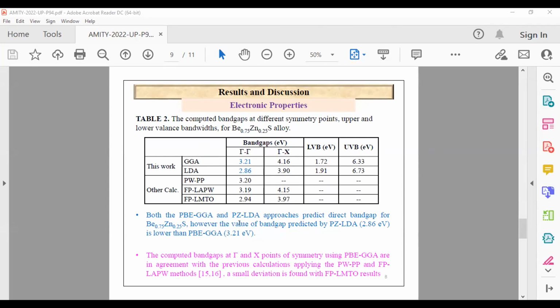We can also compare our results with other calculations, and we see that the PWPP calculation also predicts a band gap of 3.20 electron volt, and similarly 3.19 by FP-LAPW calculation. But the FP-LMTO calculation predicts a band gap of 2.94 electron volt. So our results deviate from the FP-LMTO calculation, but the FP-LAPW and PWPP calculations give results similar to our calculations.